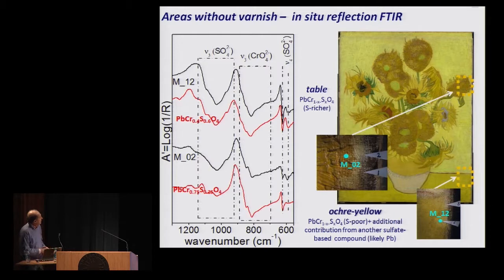And then we moved there, and we were able to find that effectively in this, which is one of the 6-7 paintings by Van Gogh that we examined there, it was possible to characterize that indeed here there is one of the pigments that is suspected to be subject to alteration because it contains a large quantity of sulfates, while in this region, for example, there is no risk because the pigment contains a low quantity of co-precipitated sulfates.